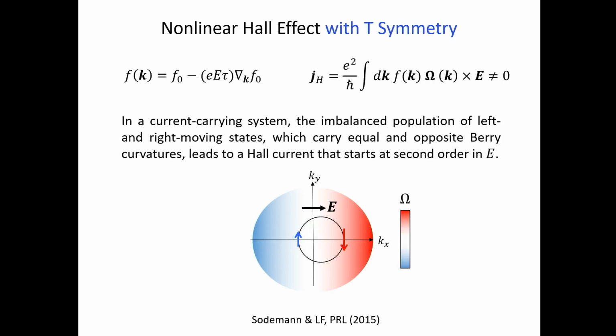But now let's look at the Hall effect beyond linear response. We realized that if we go beyond linear response, we can think about a current-carrying state driven by an external electric field. In this case, there will be more right movers in the same direction as the electric field than left movers going against the electric field. So there's a population imbalance between left and right movers. When the left and right movers carry opposite Berry curvature, guaranteed by time-reversal symmetry, this population imbalance will then lead to a net Berry curvature. And this amount of Berry curvature is proportional to the applied electric field.